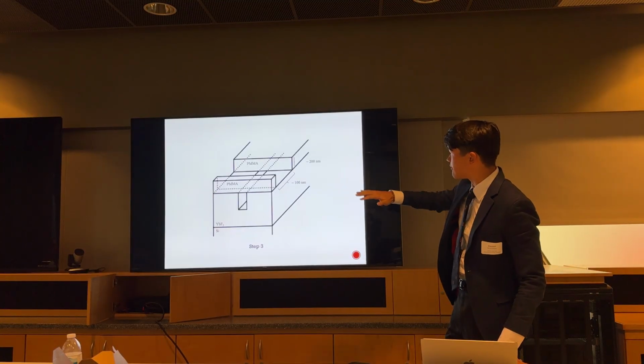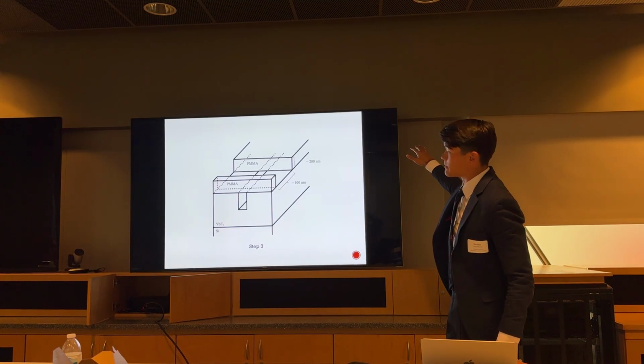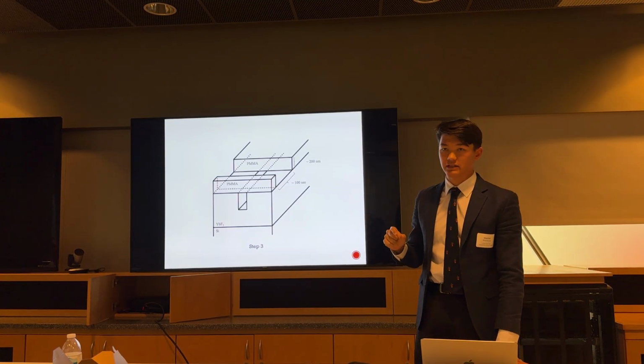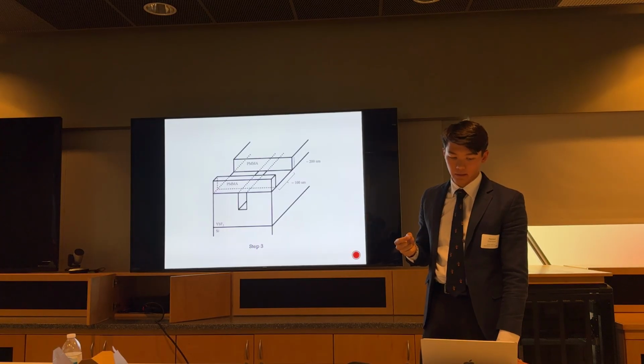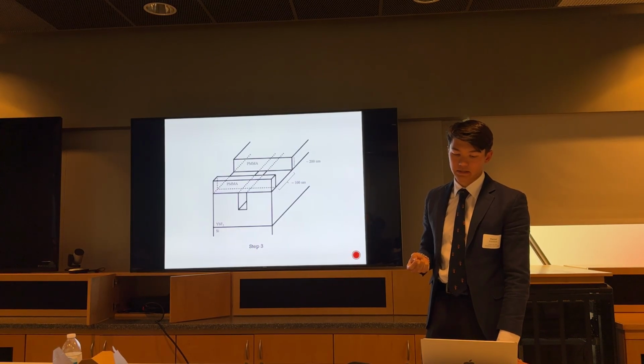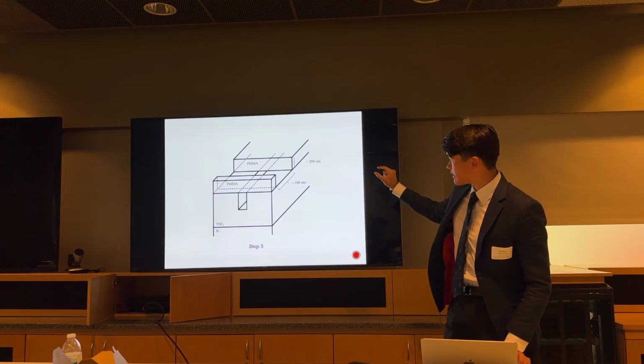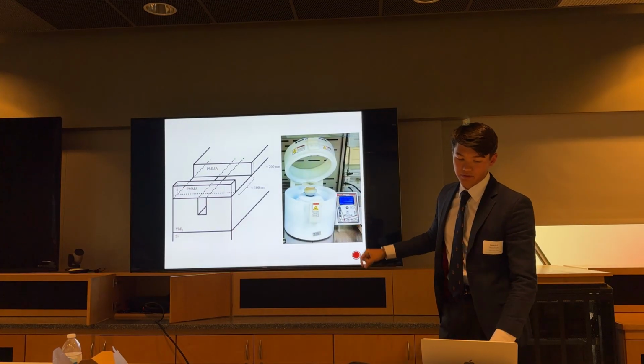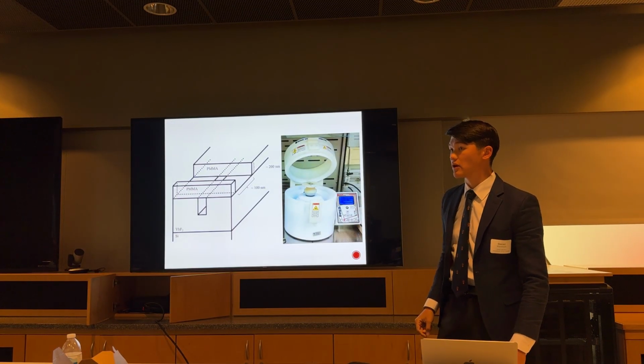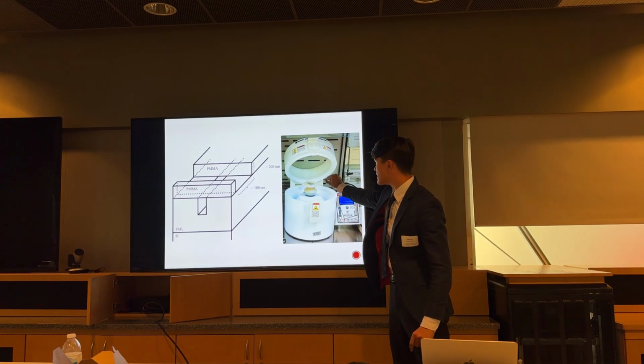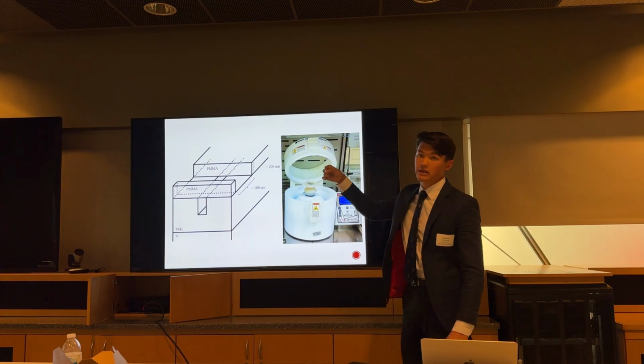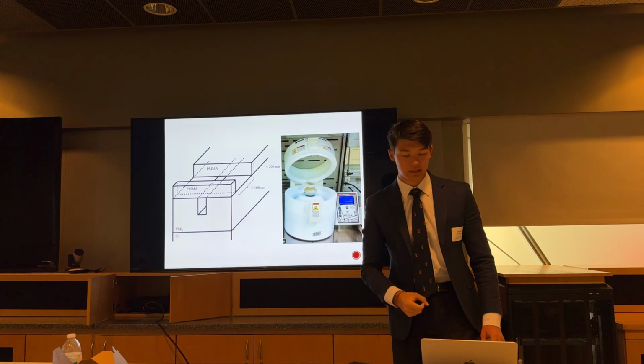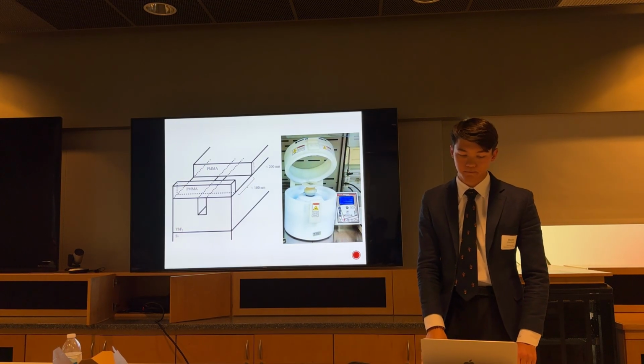and now we cover everything at the top with a layer of PMMA, which is a polymer, and it's a very conventional electron beam resist. And we create that very thin layer of 200 nanometers or so by using a spin coating machine like this. We place the sample right here and put liquid PMMA on the top, and by spinning it extremely quickly, we can create such a thin layer.